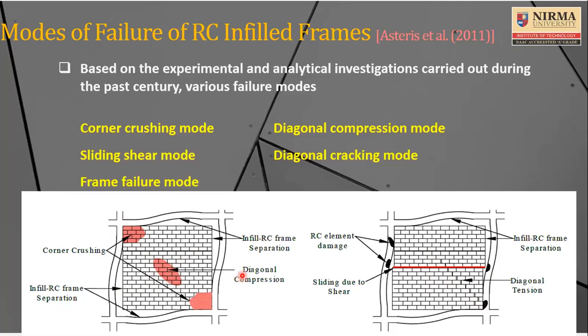And there are two other very important types of failure that we were able to see. Because this reinforced concrete framework is non-integrally built with the masonry infill, because of lateral loading you find that the RC frame is likely to undergo deformation, and that too in double curvature most of the time, and because of that the masonry infill loses its contact with the frame. As you can see, the infill and RC frame get separated on the tension side.